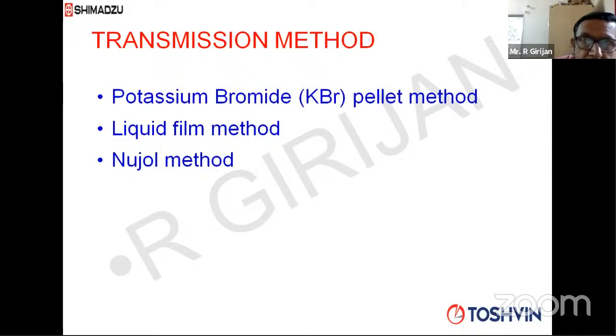The solvent will go off, and this will give a very thin film, and that's what is called the thin film method. Otherwise, if it is a liquid sample, also sometimes a viscous liquid sample, you can just spread it as a thin film on a crystal and dry it under an IR lamp, and then you can record the spectrum. That's called the film method, liquid film method, or Nujol method.